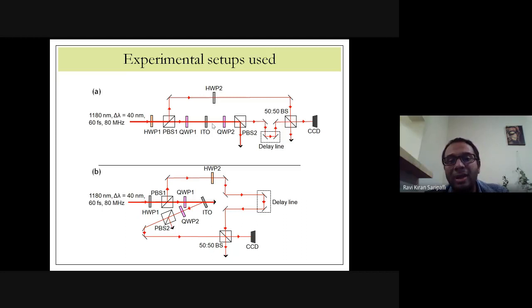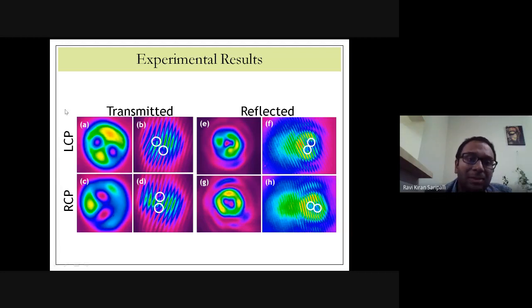So we use again a quarter wave plate and a polarizing beam splitter to separate these two components. And the component which is converted, or the right circular polarized beam, has this vortex, and that you can see in the CCD. And of course, you also interfere with the Gaussian to be able to see that image on the CCD. And we repeated the same experiments in the reflected part as well. And as you can see, when you come in with the left circular polarized beam, in the right circular component, you see this vortex generation.